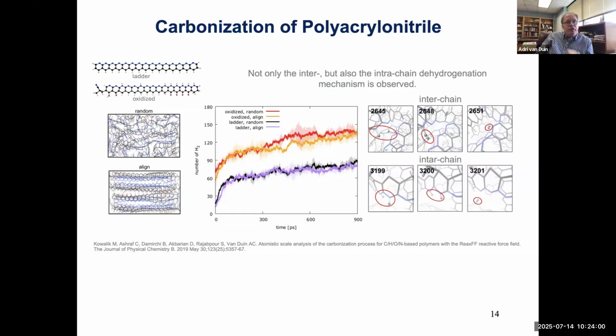So now, naively, you would say that this looks essentially already like a carbon fiber. So if you graphitize it, you think, okay, we just remove those nitrogen atoms at the top, replace them with carbon, and we're done. It turned out that when we actually do ReaxFF simulations, it is not as simple as that. We actually see indeed that there's chain dehydrogenation, so we lose some hydrogens and we do indeed see carbonization, but there's also extensive communication between the chains, and so we see carbon growth in the direction of the chain, but we also see graphitic growth between the chains, so it is much less predictable than we thought initially.